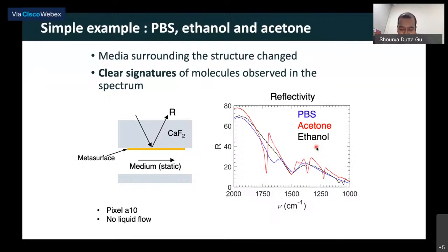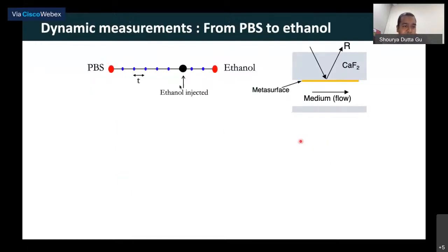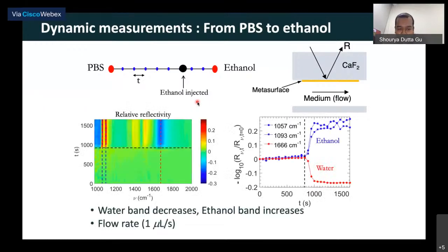Now, you're not limited to doing static measurement. You can actually do dynamic measurement, which is shown here. So we start with the chamber filled with PBS, which is close to water, and then after some time we flow ethanol. We start injecting ethanol, and it will take some time for the ethanol to completely replace water or PBS in the chamber, right? During this whole process, you can measure the signal and get a plot like this. The horizontal axis is wave number, the vertical axis is time, and the color represents the signal that you're measuring. The reference here is of course the initial state of water.